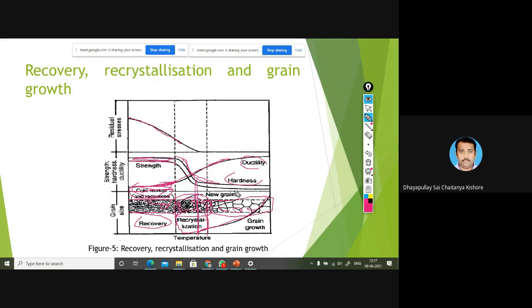So that's why, during the forming process, you don't have to increase the temperature beyond the grain growth zone. Whenever the grains are subjected to grain growth, less than that, you only have to maintain the recrystallization temperatures. Due to that, it will maintain the strength and hardness. If there is an increase in the grain sizes, that will affect the strength and hardness. There is a reduction in the strength and hardness, but there is good ductility.